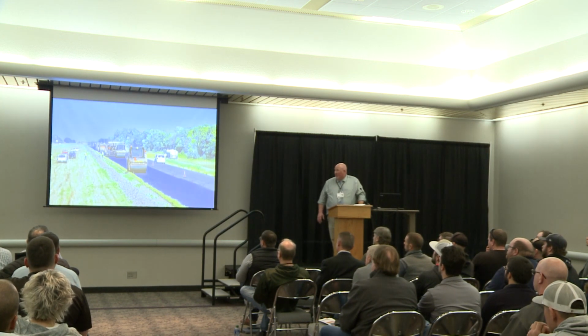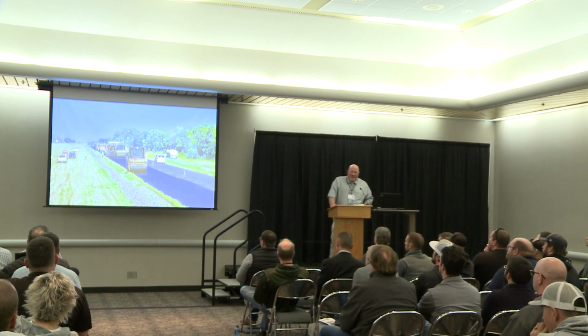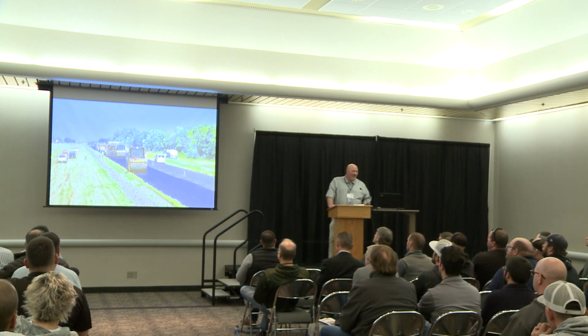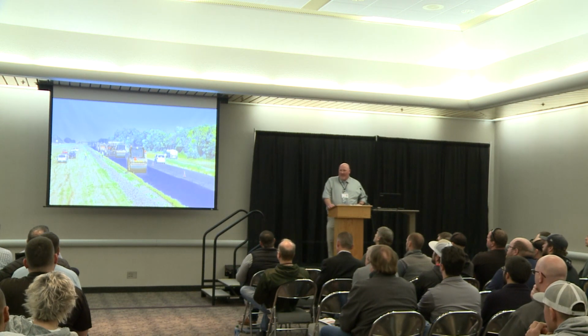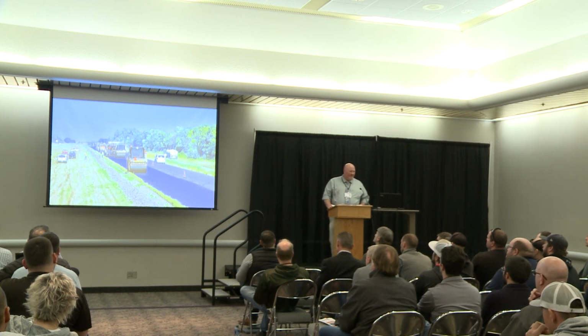And this is just a picture of the asphalt laid down. It goes down similar to your normal mixes with the exception that this is very temperature variable. A windy day will suck the heat out, and it's hard to get compaction on an SMA mix if you lose your heat. So on a good windy day, even if it's 90 degrees out, the rollers are going to be almost on top of the paver, which is different to see, but if they're not up there, they won't get density.